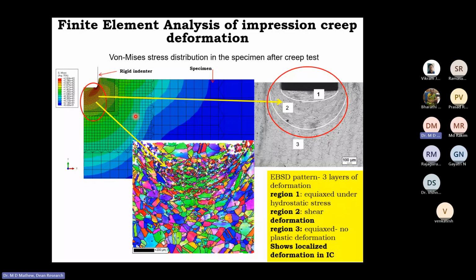This shows some of the finite element analysis that was carried out. So this is an EBSD micrograph. You can see here that there are 3 layers of deformation. A region 1, that is this one, where the grains appear to be somewhat equiaxed, which would lead us to assume that the material in this region is under hydrostatic stress. That is what you see here. And then a region 2, where you will find that the grains are all deformed. They have been subjected to shear stress. So there's a lot of shear deformation happening in this region.